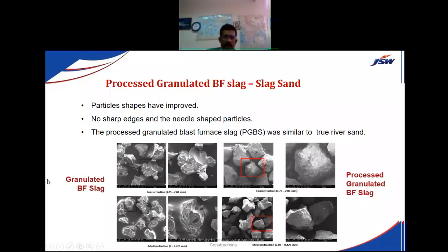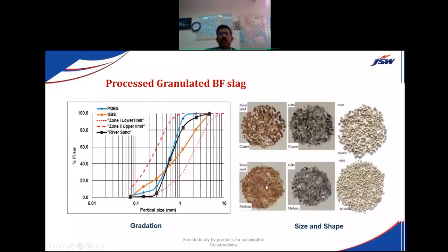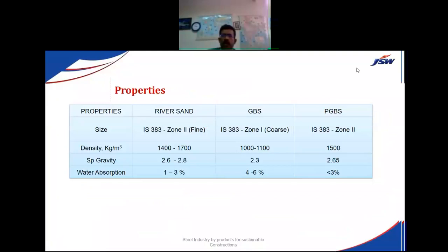The granulated blast furnace slag is the stage getting converted into the finished product. The processed one has round-shaped particles and also a uniform particle size. Looking at the gradation curve, the processed slag, what we call manufactured sand, meets the requirement of gradation Zone 2 specifications as per river sand. So you can see a changed product. The density has improved to 1500 kg per meter cube from the GBS, which was the earlier raw material, and the specific gravity is 2.65, meeting the river sand specifications.